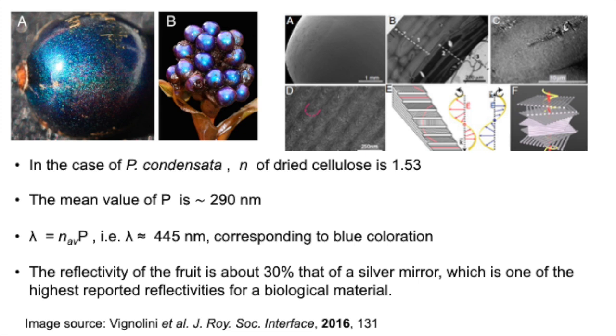Using the relation presented in this equation and inserting the values mentioned above, yields a reflected wavelength of roughly 445 nanometers, corresponding to blue coloration. Remarkably, the reflectivity of the fruit reaches about 30% of that of a silver mirror, making it one of the highest reflectivities reported for any biological material.